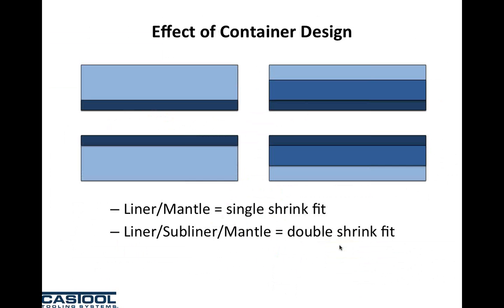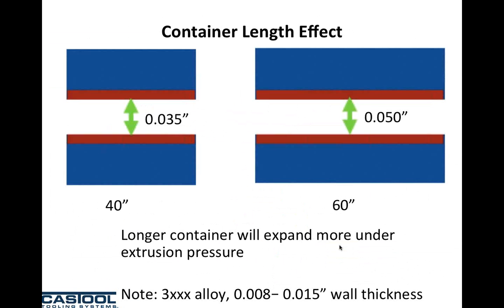We also worry about the physical dimensions of the liner during extrusion. All of the people that make containers put a shrink fit between the liner and mantle to try to add strength. A 3-piece container is definitely stronger than a 2-piece container. What's interesting, if we look at a standard 40-inch container for an 8-inch billet, the amount of expansion on the bore of a 2-piece well-made container is about 35 thou.